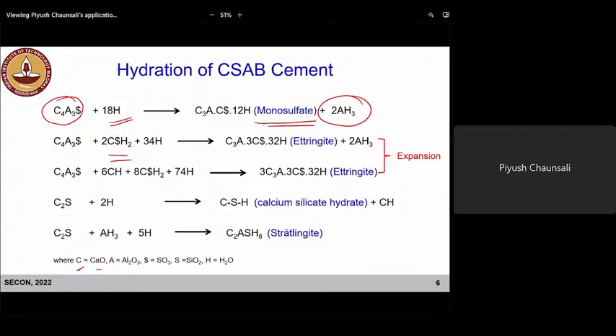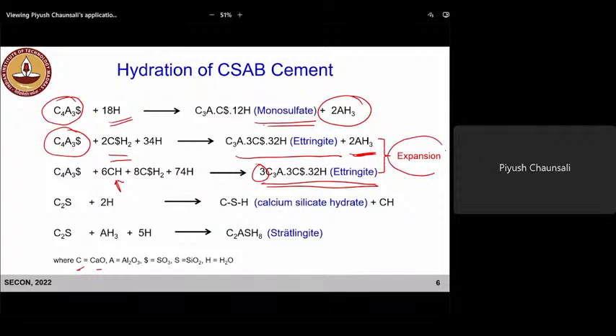So the yeelimite phase can react with gypsum and form ettringite. This is the ettringite, the AFT phase, which also gives you aluminum hydroxide. Now, if CSAB cement is mixed with Portland cement, or we supply additional calcium hydroxide, CH, now we have a larger amount of ettringite which is formed. So these two reactions contribute to expansion, and we'll see how we leverage that expansion to our advantage.